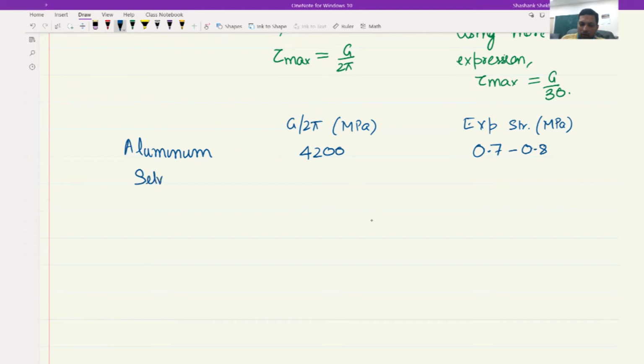For silver, so we are talking about single crystal, so yield strength is not really an appropriate term here. It is the minimum critical shear stress required for deformation of the single crystal. For silver, it should be 4800, and what we get is 0.4 to 0.5. So even if you take this as G by 6 as an exaggeration, and you go for G by 30, which would mean divided by 5, but still what we see is that we are orders of magnitude away. So this is the experimental strength, and this is what theory predicts based on assuming that this is how the deformation is taking place by slipping of planes past each other, which clearly implies that our assumption is wrong.